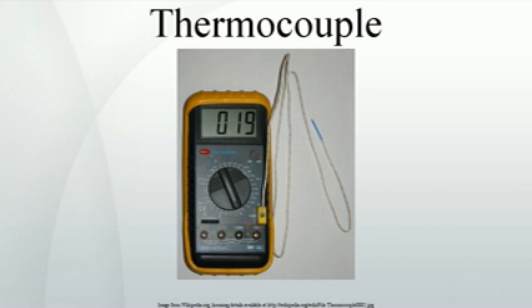Chromel-gold/iron alloy thermocouples. In these thermocouples, chromel-gold/iron alloy, the negative wire is gold with a small fraction, 0.03-0.15 atom%, of iron. The impure gold wire gives the thermocouple a high sensitivity at low temperatures, compared to other thermocouples at that temperature, whereas the chromel wire maintains the sensitivity near room temperature. It can be used for cryogenic applications, 1.2-300 K and even up to 600 K.